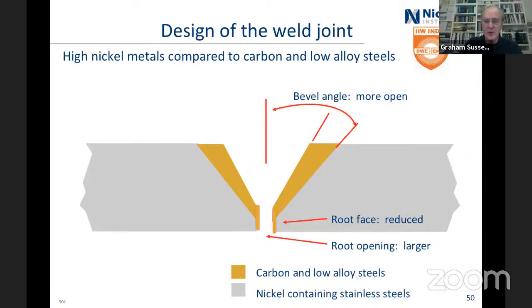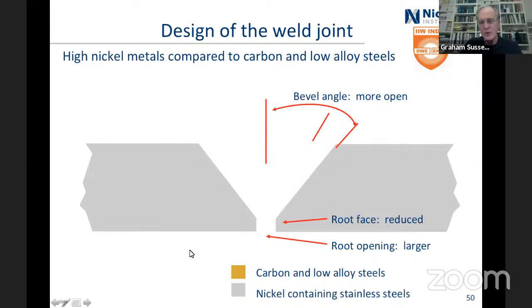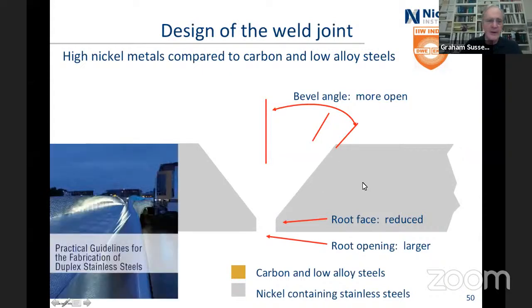Design of the joint, I'm sorry for the fiddling in the middle, but that's carbon steel roughly. And if this worked, yep, and that's roughly what you should do with the duplex. It's as crude as you can be, but bigger gap there, less there, and more open because it's more viscous. If you want to know more about that, the practical guidelines for the fabrication of duplex stainless steels is available either from IMOA or from Nickel Institute.